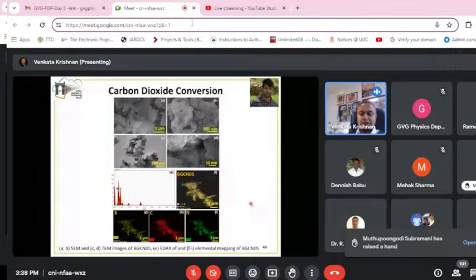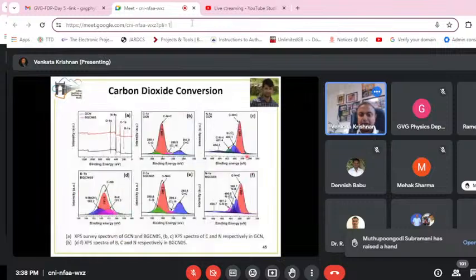We also characterized using SEM and TEM techniques to find out the morphology, and we found again in this case sheet type of morphology, because we were aiming for sheets and it's an established protocol, so we were getting sheets. Then we did a detailed XPS analysis, which indicates how the different elements present in this catalyst are interacting with each other and what are the oxidation states of the different elements present.